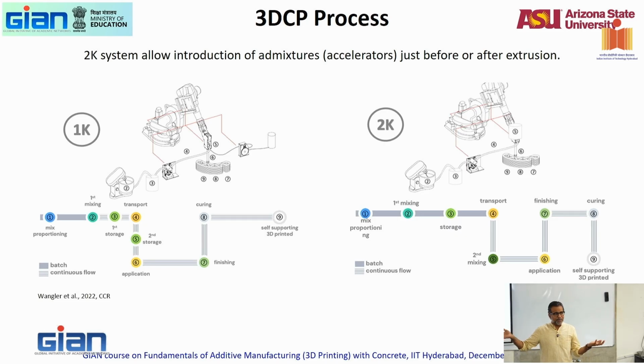It's not hydrating completely here, but you see how the volume has increased. That increased volume fills up the space, increases the stiffness, and helps hold the shape much better. So that's the benefit of adding an accelerator at the tip of the nozzle just before it comes out. You don't want to do it ahead of time. You don't want to do it while the material is within the extruder, because it'll get stuck in the extruder.